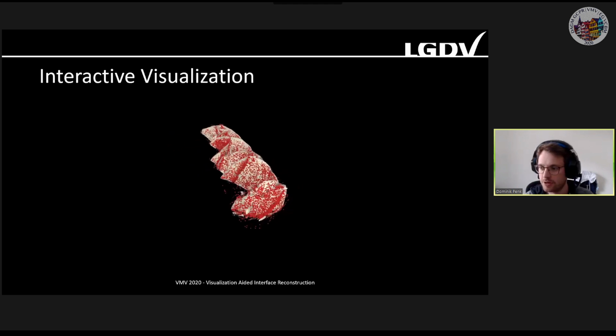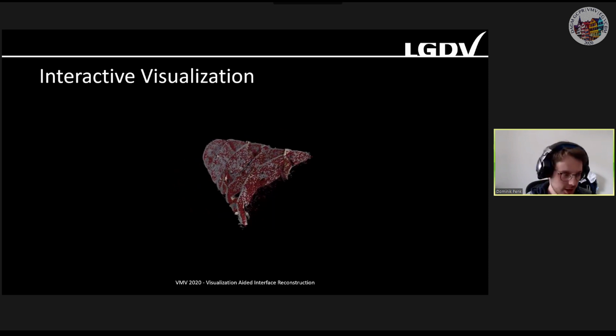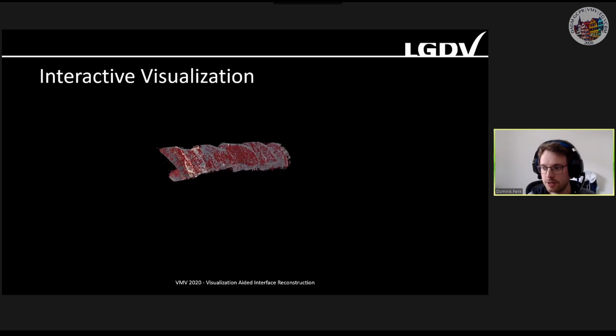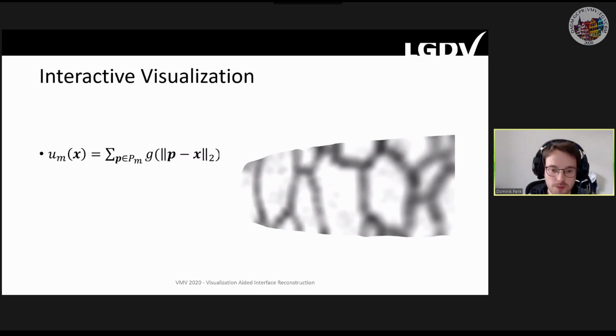One example you see here in the center, where we once again visualize the surfaces for the aluminium atoms. Important to note here is that we don't have an actual surface representation yet, it's just a visualization. We do so by visualizing the density field estimated from the filtered point cloud. To get this density field, we first splat all the atom positions by using Gaussian kernels. And this yields a density estimation, like you see on the right-hand side. This is a 2D slice, of course. The dark parts are regions of high density, and white means there's basically no density in here.